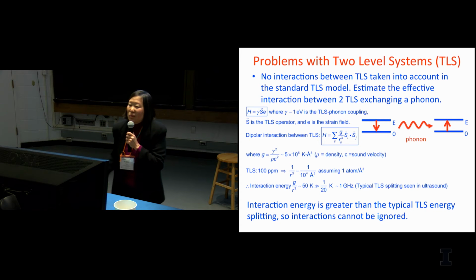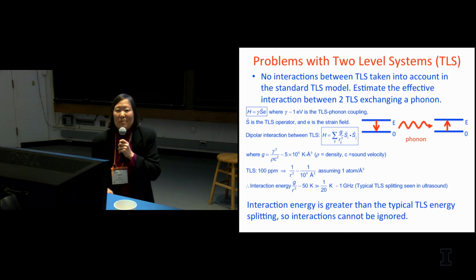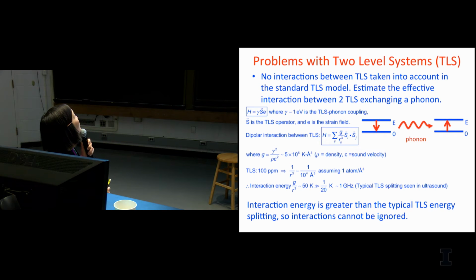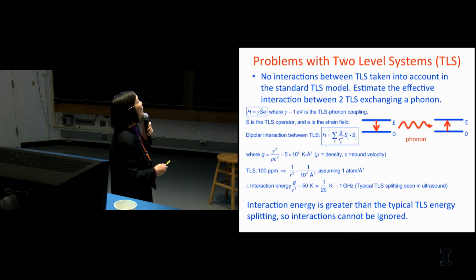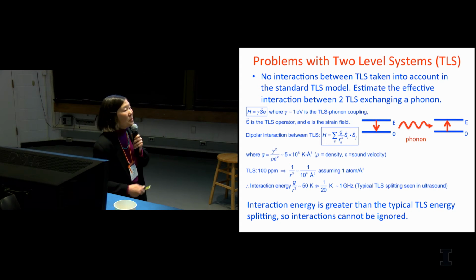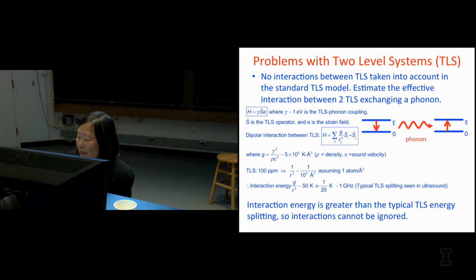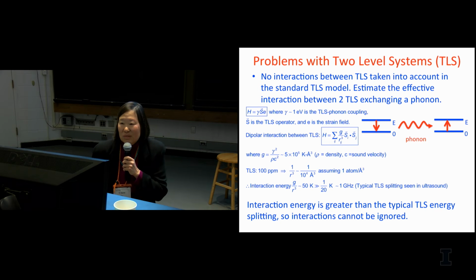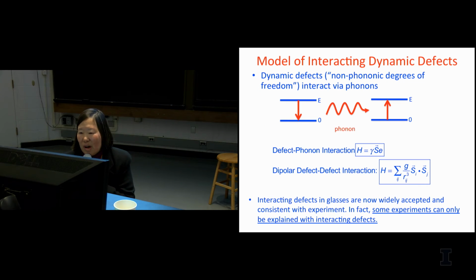And finally, the standard model of two-level systems did not include interactions unless absolutely necessary. And so there should be interactions. If you think about it, you've got the phonon, which is coupled to the two-level system. Here E is the strain field, S is the two-level system, gamma is some coupling. And so the two-level systems should be able to talk to one another by exchanging virtual phonons, and that would give you a dipolar interaction. If you estimate the size of that interaction, it's much larger than the typical two-level system splitting seen in ultrasound. So you really can't ignore interactions, and I think that's really the contribution of this paper, to say that you really do have to put interactions into the model.